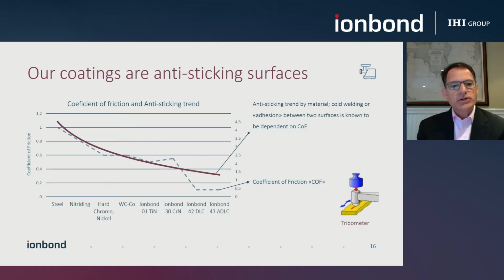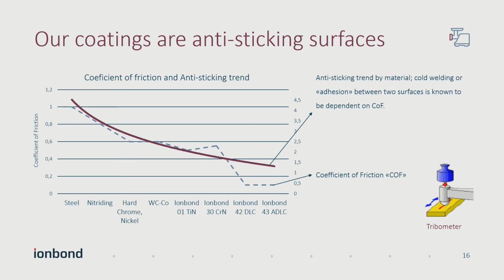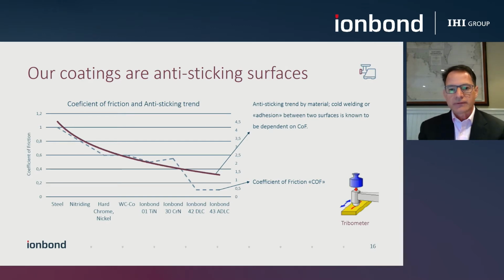The other piece we wanted to share with you was some of the characteristics for the anti-sticking. What we're trying to show in this graph is, on the left-hand side, the coefficient of friction. Using the same standards that we had used in the previous materials: steel, so uncoated, on the left, nitriding, hard chrome, tungsten, and then the various Ionbond coatings that we've been discussing. As you can see, by applying one of our thin film coatings, we can substantially reduce the coefficient of friction over the particular component.